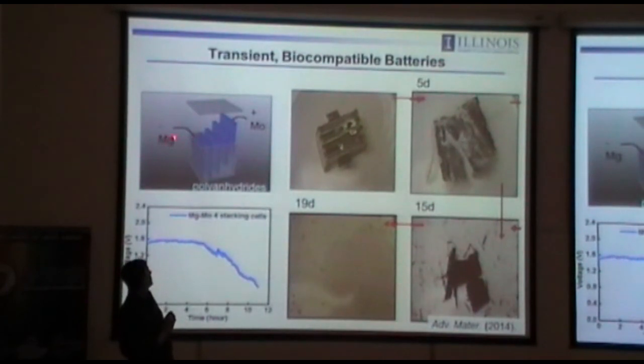Water-activated electrolytic cell composed of magnesium foils and molybdenum foils embedded in a bioresorbable polymer casing, polyanhydride. And so you have energy density here about the same as a lithium-ion battery. Power density is about a factor of 10 lower. But do you think we can optimize that?